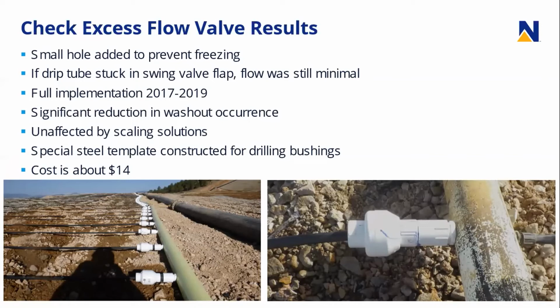We did find that, especially under lower pressure conditions, the drip tube sometimes would get stuck in the flap in the check valve, but again, it was a minimal flow that was going through it. So not the blast of solution coming out of the feed header straight towards the side slope. So they tended to still prevent the washouts. We fully implemented using check excess flow valves for 2017 and 2019 before we switched to primarily injection wells for production off of VLF1.